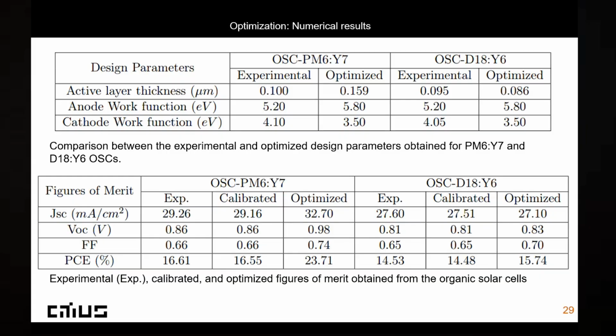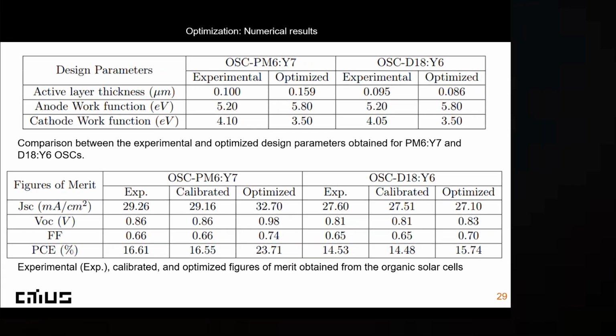This improved the short circuit current in this organic solar cell. In the second one, the active layer thickness was reduced slightly, and this improves the fill factor. And finally, with all this data, you can see the improvements in the efficiency.